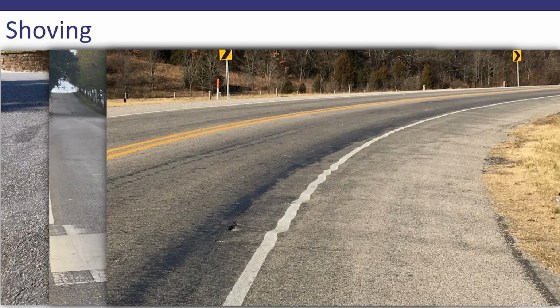And then here's an example of lateral shoving in a curve section. The best way to identify this, again, is to look at the stripe. The stripe was not painted in a wavy format, but it looks that way now. And so what's happened is traffic is actually pushing that mix around. It's not super stable. So for that, we're going to look at the square footage, figure out how much of that pavement is affected, and record it.